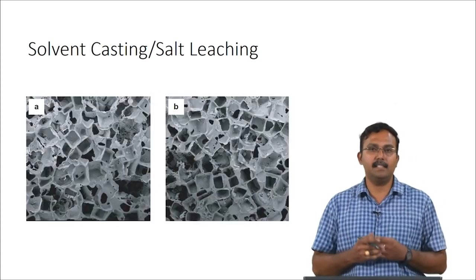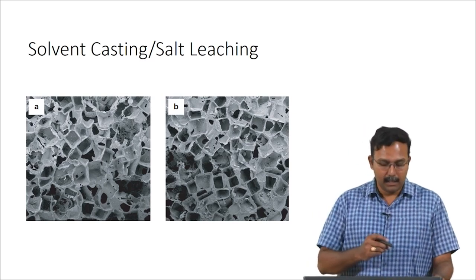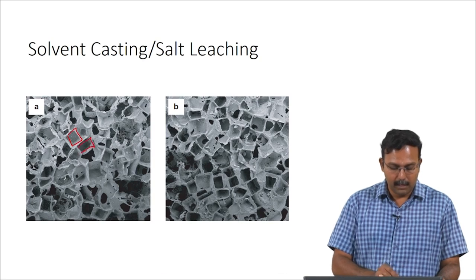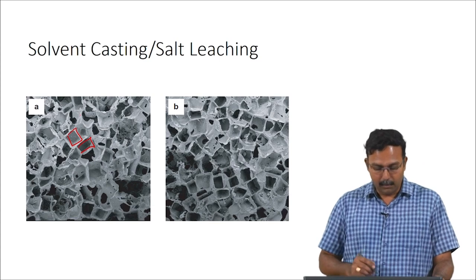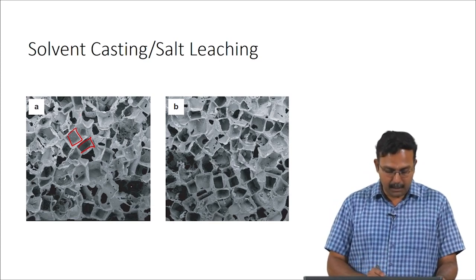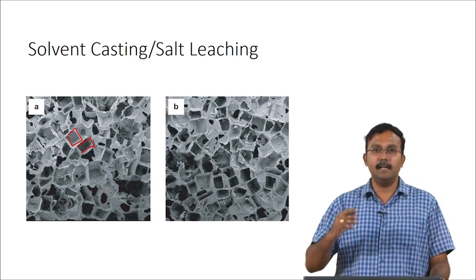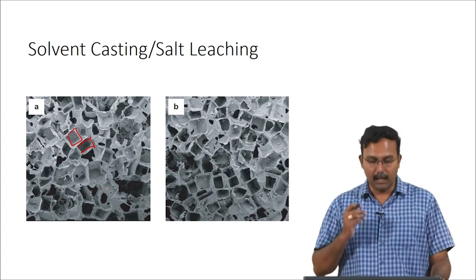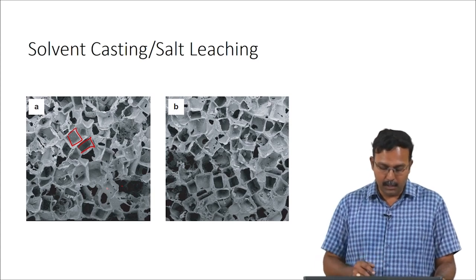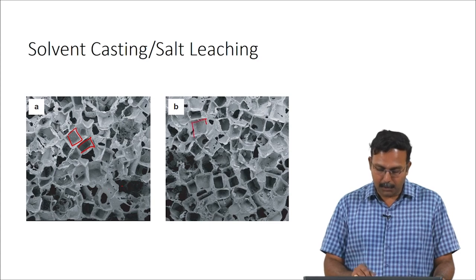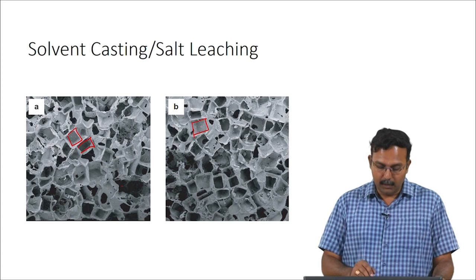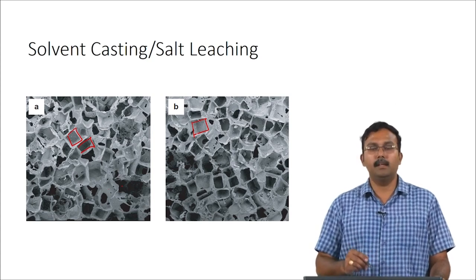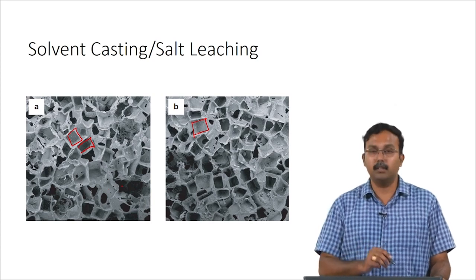These scaffolds would look like this under a scanning electron microscope — images of salt-leached scaffolds showing nice structures which are the regions where the salt crystals were occupying. When you look at the images you would also see areas which are dark black while some are grey, indicating a 3D structure with crystals formed all over creating such pores. However, one of the limitations is that in many of these pores there is very poor interconnectivity. For example, a particular pore may be fully covered — cells can attach but cannot penetrate into the scaffold. This means interconnectivity might not be excellent with the solvent casting and salt leaching method.